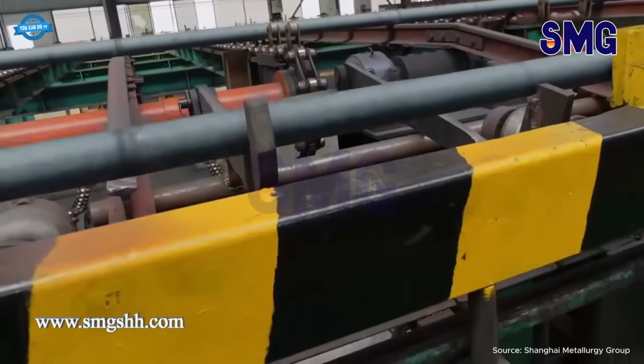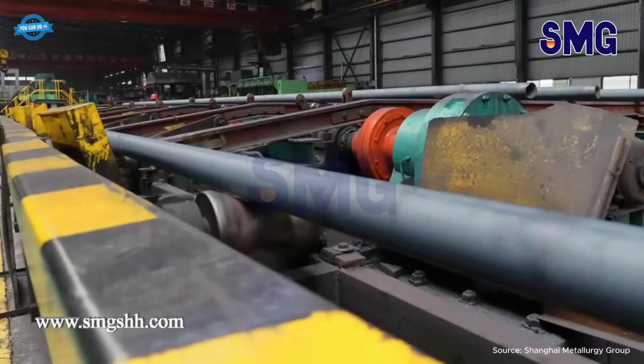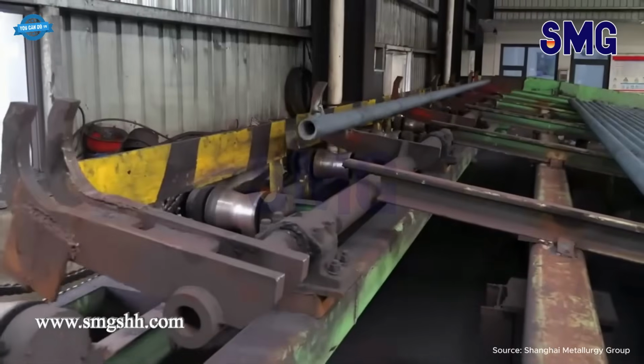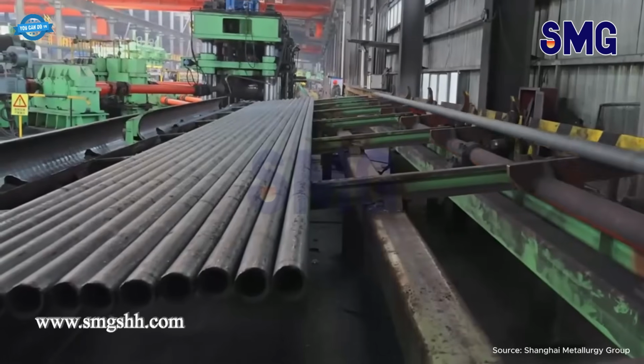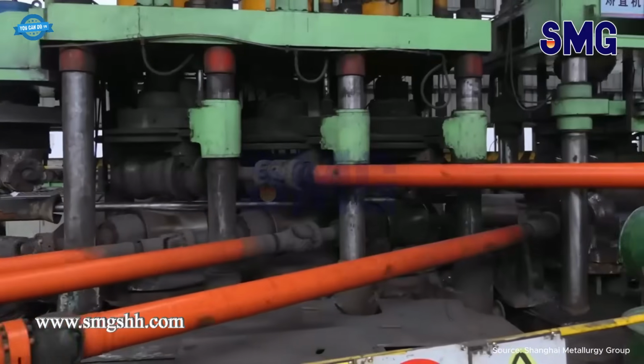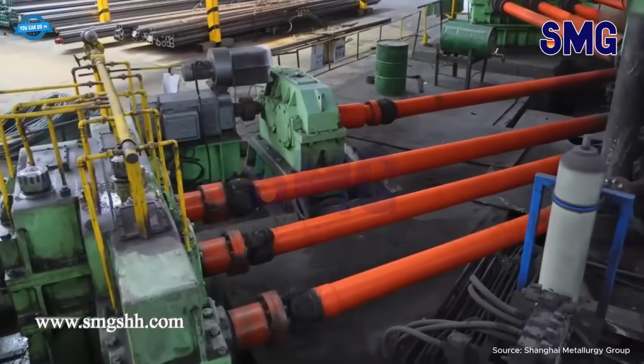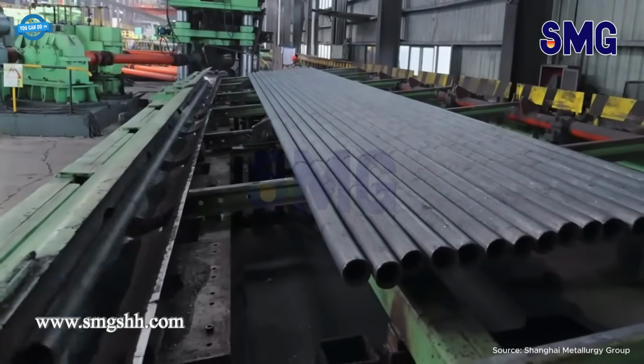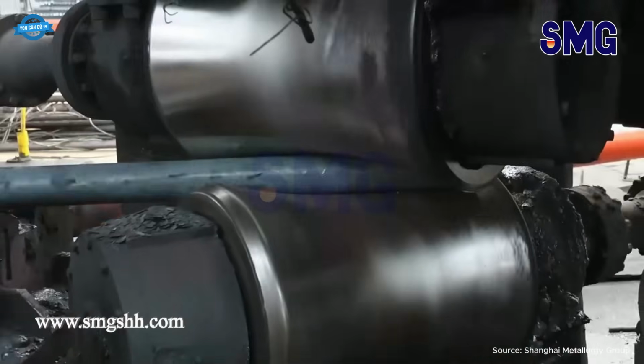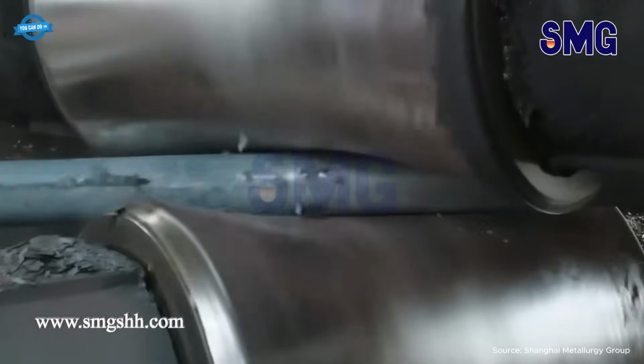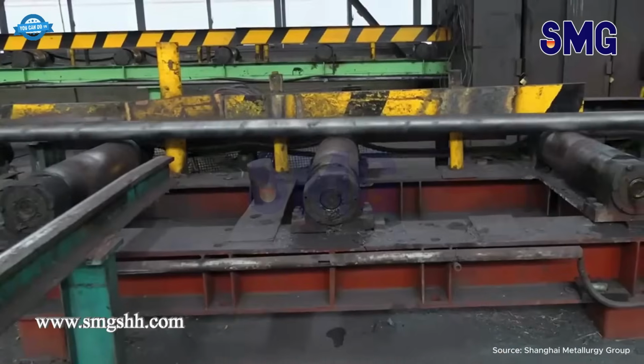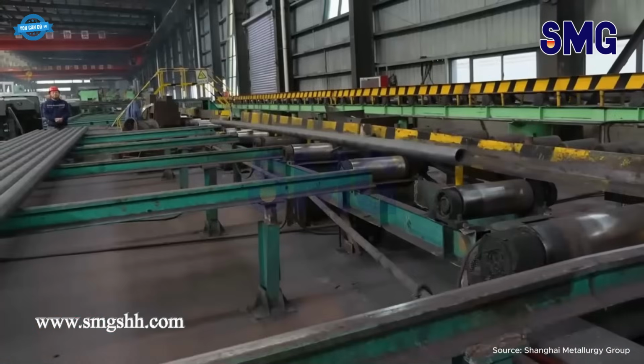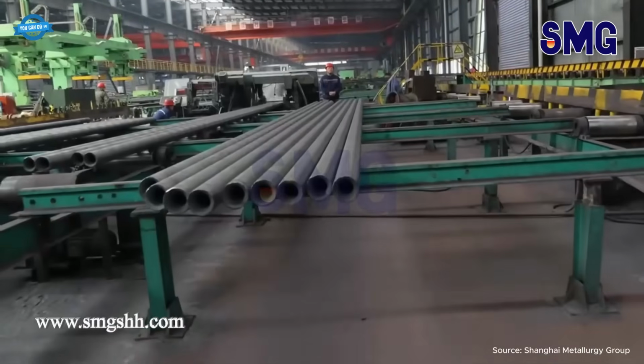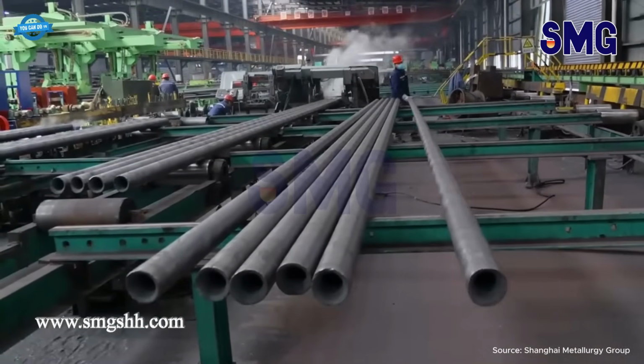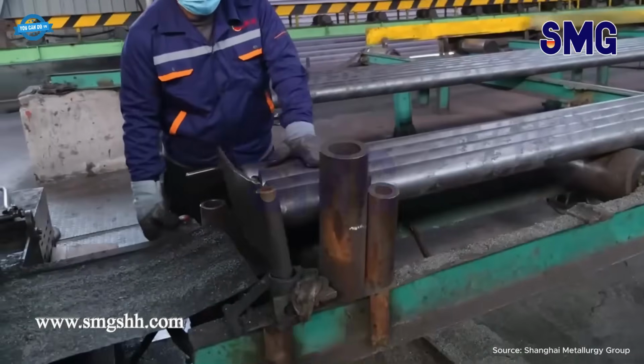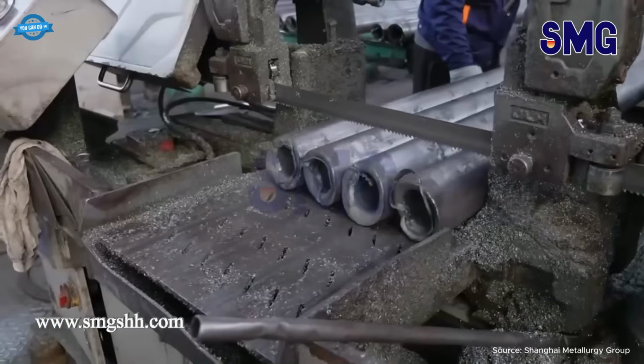The pipe then undergoes straightening via multi-roll or pressure correction systems to achieve precise geometry within tolerance limits. Fixed-length cutting follows, using sawing or plasma machines to ensure clean, burr-free ends. Next, the pipes are heat-treated, typically by annealing or normalizing, under controlled temperature and time settings, to relieve internal stress and refine structure.